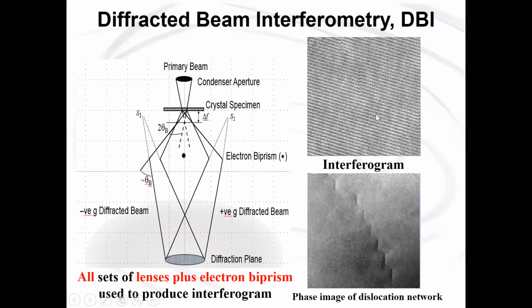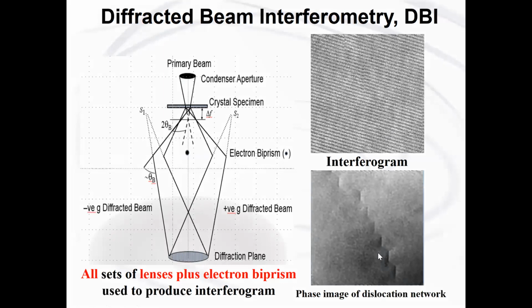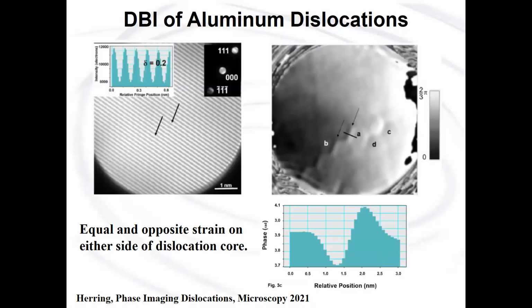On the top right here is a good example of an interferogram. When we Fourier transform this, we can get the phase, and in this particular interferogram, in the phase image, we see a dislocation network. This also shows an example of an interferogram. It has very high contrast fringes. It's the two 111 beams interfering in an aluminum material. And when we reconstruct that, we see that we have a nice dislocation network in here.